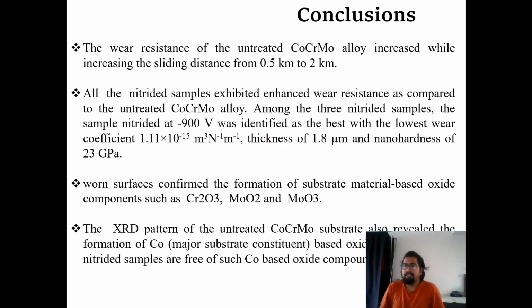In conclusion, I would like to say that the wear resistance of the untreated CoCrMo alloy increases with the increase in sliding distance, and in the case of nitrided specimens, the best wear and friction combination we found was for the 900 volt, which had the lowest wear coefficient, 1.11 times 10 to the minus 15, with a nano hardness of 23 GPa, and this hardness is almost 1 to 2 times harder than that of the commercially available nitrided specimen.